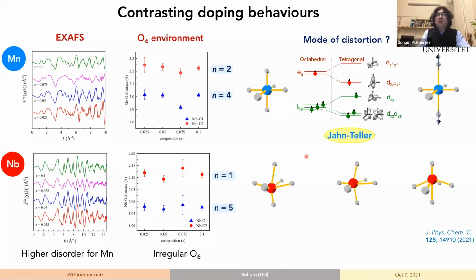And when we look at the niobium, we looked at all different kinds of models, and we found there's a strange 1+5 combination of distances. So it has one long distance and five short distances. We tried modeling in different ways, and we saw that only a model where niobium off-centers along the 0-0-1 direction is consistent with the EXAFS data that we see.